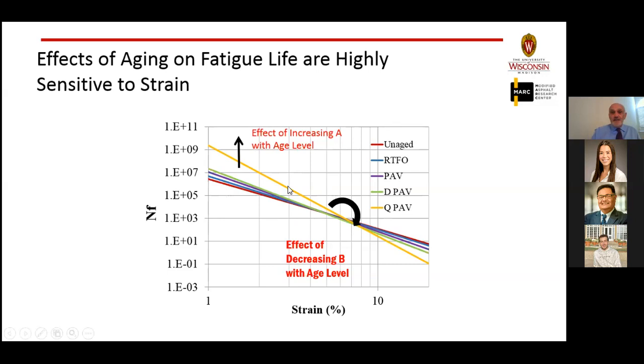In fact, many people said thick pavements behave very well with aging and fatigue is not affected by aging. Well, because these thick pavements could be under very small strains, and therefore when the material is aged, the modulus goes up and that will reduce the amount of damage in the layer itself. However, if you miss this point and go beyond that, you will see the traditional effect of aging, which is as the aging increases, the slope of the line increases, and therefore the number of cycles to failure will decrease dramatically.